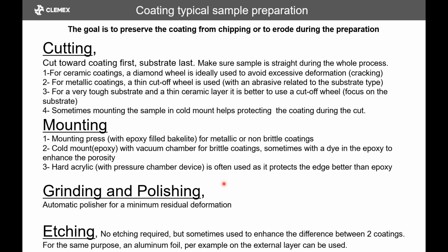Since this is my former life, I want to give a bit of an overview of how to prepare a sample. I know that there are many companies doing this, but just to give you an overview. So when you're working with a coating, what you want is to make sure that you cut toward the coating first and end with the substrate. And also you want to make sure that it will be straight. If it's at an angle, you will bias your thickness measurement because it will be larger. So it needs to be straight.